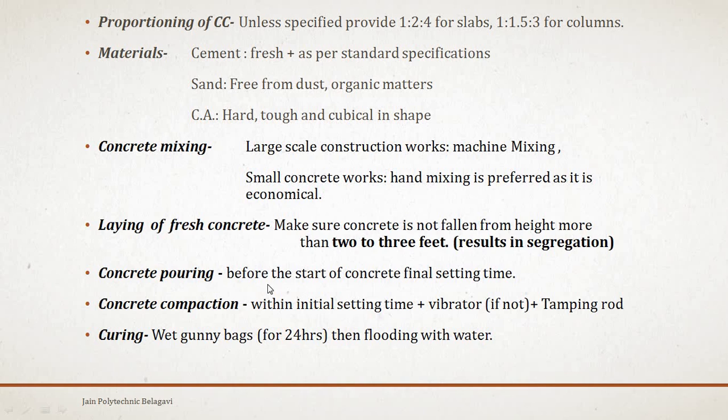Now concrete pouring. The concrete should be poured or laid before the start of the concrete's final setting time. Here the final setting time is 10 hours, so the concrete laying should be taken up early. Concrete compaction should be done within the initial setting time.